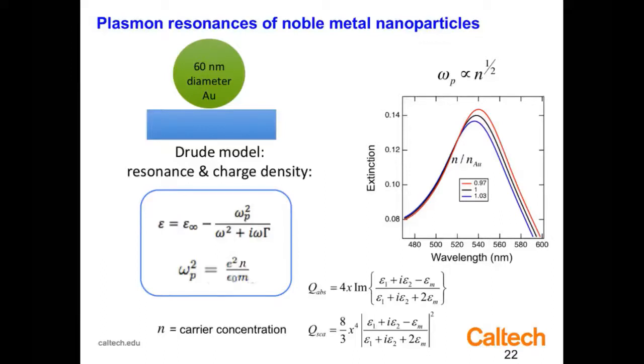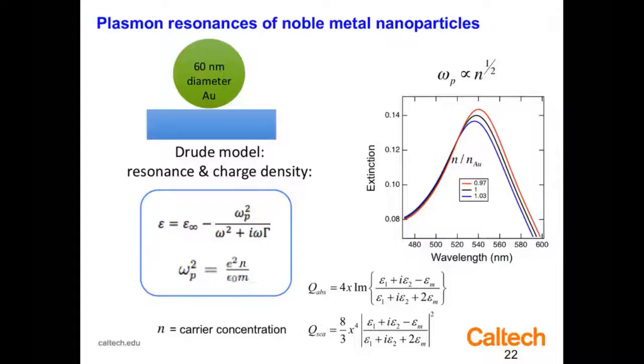This is an experiment that we did. This is by Anna Brown, a talented student who did this experiment, putting metal nanoparticles essentially inside an electrochemical cell with an ionic liquid. And we had to apply such a large potential, we actually went through the gold redox potentials. We actually oxidized gold and reduced it. The data I'm showing you here are outside the range where we did redox. It's all gold. It's not a transformation due to gold oxide.